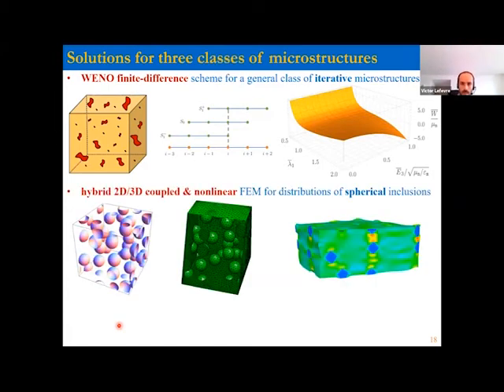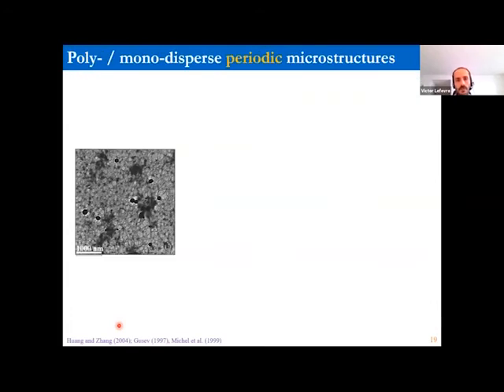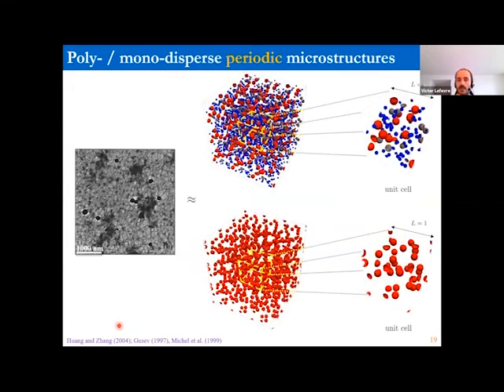What I want to show you next is what we did for composites that are a bit more realistic, where now the particles are spherical in shape. So what we want to do is try to represent the overall isotropy of these composites that's observed experimentally. And there's a good way to do that computationally. The idea is to use periodic composites that are made out of the periodic repetition of a cubic unit cell, where you have a random distribution of particles in the unit cell. And so even though these are periodic composites, their behavior is not exactly isotropic, but you can check a posteriori that it's actually very close to being isotropic.